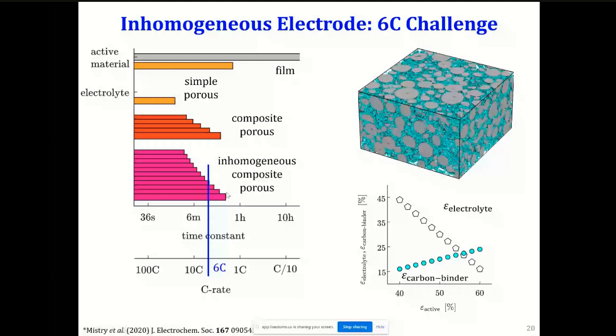And again, keep in mind, this time constant scales with the square of thickness. So if you go from a 50 micron thickness to say 75 micron thickness, this time constant is going to double, a little bit more than double actually, 2.25 times, right? So the actual challenge for XFC is simultaneously doing 6C charge on a thick electrode with higher active material packing, right? And minimizing the heat generation and minimizing the plating as much as possible. And I'll talk about it in a minute.